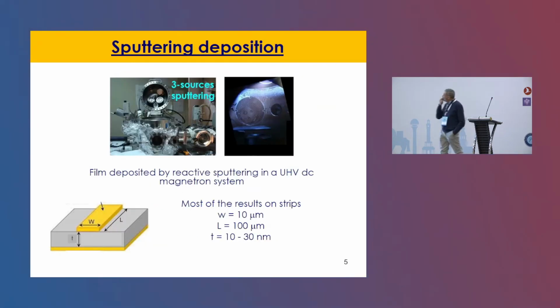All the results which I will present here are on very easy systems. All the films and systems have been deposited by a UHV sputtering system, and the geometry is very simple: just a strip of the order of 10 micrometers wide, and the thickness of the films goes between 10 and 30 nanometers. Sometimes they are thinner, but I will explicitly say when this is the case.